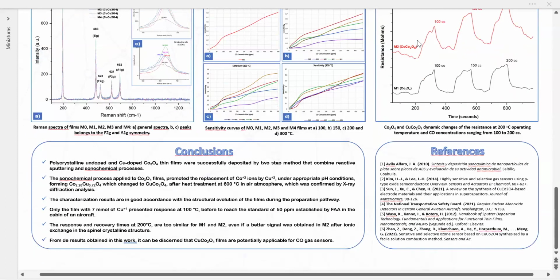From the results, it's concluded that the polycrystalline undoped and copper-doped cobalt oxide thin films were successfully deposited by a two-step method that combines reactive sputtering and sonochemical processes. The sonochemical process applied to cobalt oxide films promoted the replacement of cobalt 2+ ions by copper 2+ ions under appropriate pH conditions, which was confirmed by X-ray diffraction analysis. The characterization results are in good accordance with the structural evolution of the films during the preparation pathway.